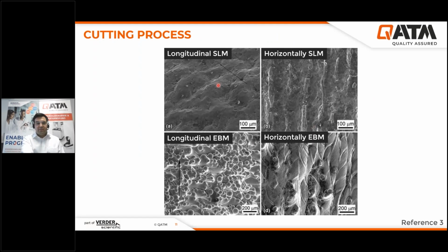We should be aware that the properties of additive manufactured samples are not isotropic, they are anisotropic. It means that in different directions, we have different mechanical, physical and microstructural properties. Here we can see, for example, the microstructure of longitudinal selective laser melting and, on the right-hand side, horizontally. And below you can see the longitudinal electron beam melting microstructure in comparison with horizontally. And they are different from each other. We should be aware of which direction should be evaluated.